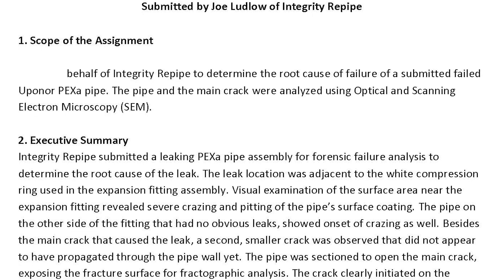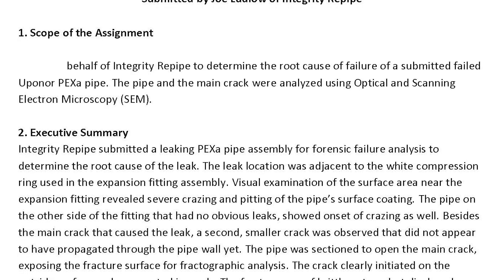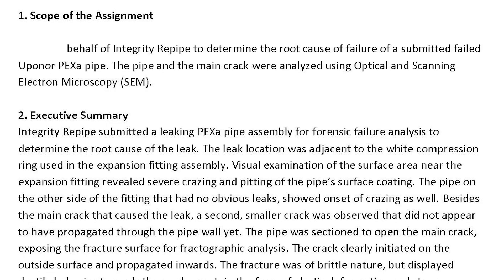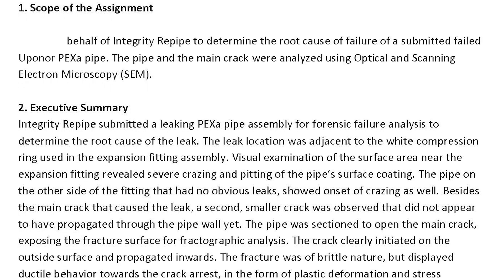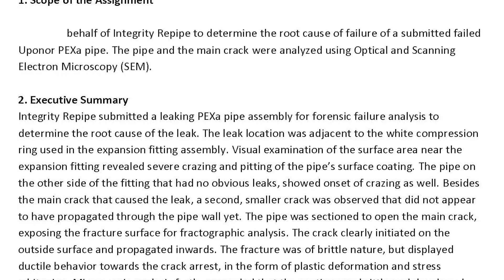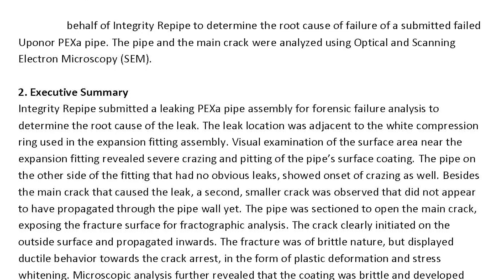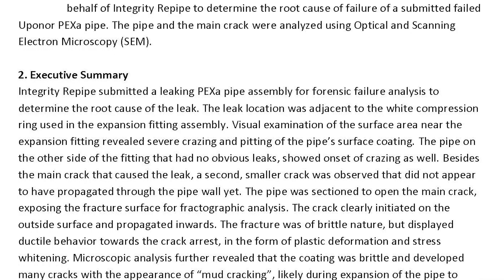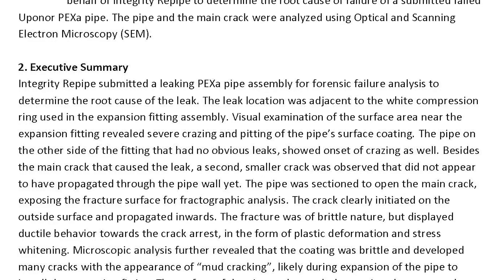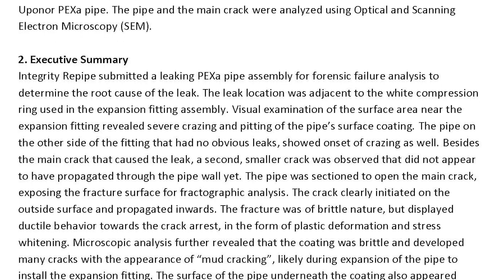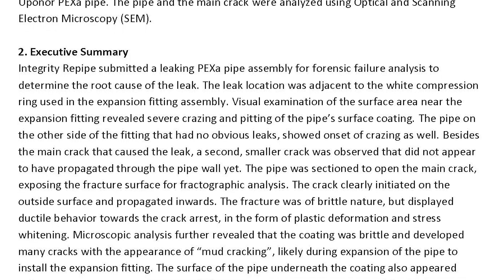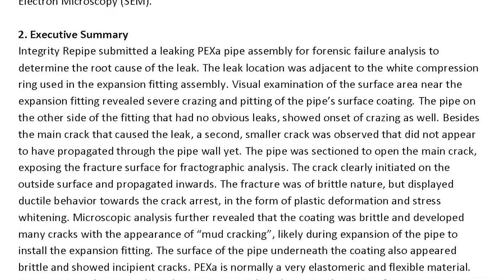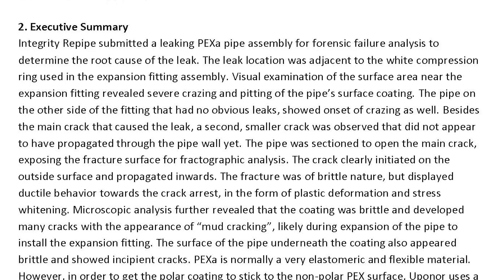The pipe and the main crack were analyzed using optical and scanning electron microscopy (SEM). Executive Summary: Integrity Repipe submitted a leaking PEX-A pipe assembly for forensic failure analysis to determine the root cause of the leak. The leak location was adjacent to the white compression ring used in the expansion fitting assembly. Visual examination of the surface area near the expansion fitting revealed severe crazing and pitting of the pipe surface coating. The pipe on the other side of the fitting, which had no obvious leaks, showed onset of crazing as well.